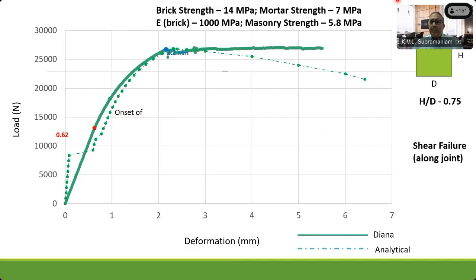Now, with this model, we were able to predict the response of different masonry assemblies. So here, what we have is a masonry assembly of a certain height and width, which is made up of brick of 1 GPa, which is what we tested in our program, a masonry strength of 5.8 MPa, and this is the masonry made up of the weak mortar. Now, we are trying to predict the response of this masonry structure with an H over D of 0.75, which is basically a squat wall subjected to a compression of 0.5 MPa. And if I try to get the lateral response of this, this is what is predicted by the numerical model.